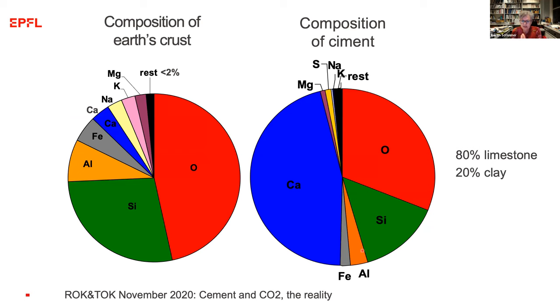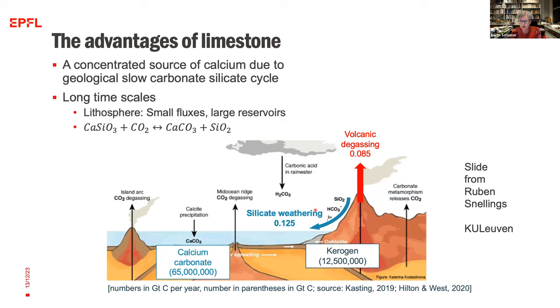Well, limestone is very convenient because it concentrates the calcium. And if we look at the composition of the Earth's crust here on the left, compared to the composition of a typical Portland cement, of course, the huge difference you see is the much higher amount of calcium in the cement. Now, limestone is this concentrated source of calcium because of the natural carbon cycles going on in the world. And I'm very grateful to this slide from Ruben Snellings because this really demonstrates the conundrum. What we have is rocks produced by volcanoes, which have, roughly speaking, the average composition of the Earth. Over time, these weather and the basic